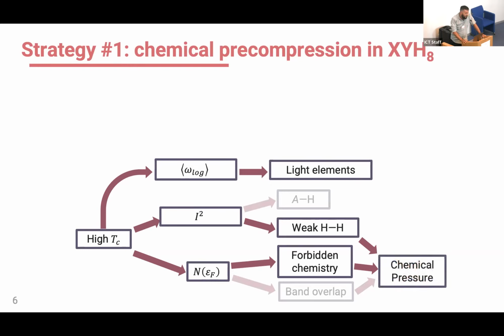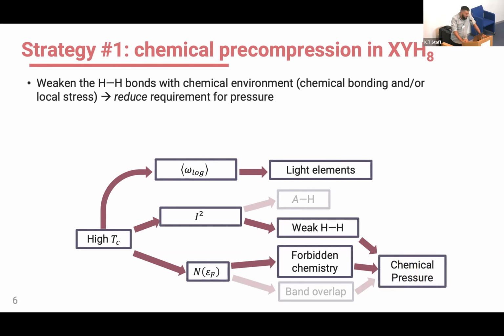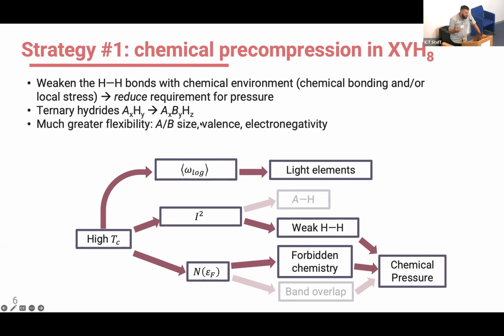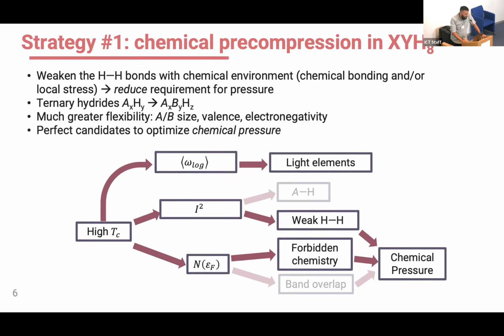Now, if we want to get rid of pressure, we can try to replace that with chemical pressure. What we mean with this not so well-defined term is that we want to weaken the hydrogen-hydrogen bonds using their chemical environment, so the chemical bonding and/or the local stress around the hydrogen sublattice, which will reduce the requirement for pressure. An ideal playground to do this is ternary hydrides. So we go from a structure that has an AXHY composition to one in which we have an element A and another element B other than hydrogen. And what we gain is a much greater flexibility, because now we can play with two different atoms to really try to optimize this chemical environment.